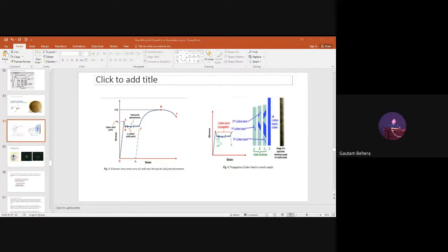So what is happening exactly? In the initial part, all the material will not deform. A particular part of the material will yield. Yielding will happen in a particular area of the specimen, and that will become strain hardened after some time. Ahead of that portion, another, softer part will get yielded. Again, it will get strain hardened, and an area above that will get yielded. Similarly, due to this kind of thing, these Luder bands are seen. Here it is already written over here. If you want to see, the same thing is written over here.